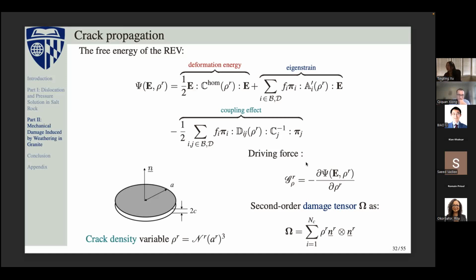So with this free energy formulation, we can easily get the driving force for the microcrack propagation by taking the derivative with respect to the crack density. And also we can define the second order damage tensor as a directional summation of these crack density variables. So that is overall the tensor which characterizes the internal variables.